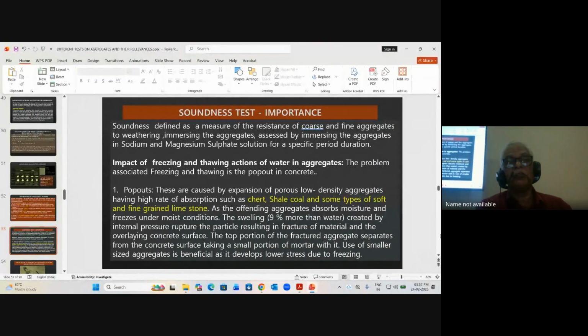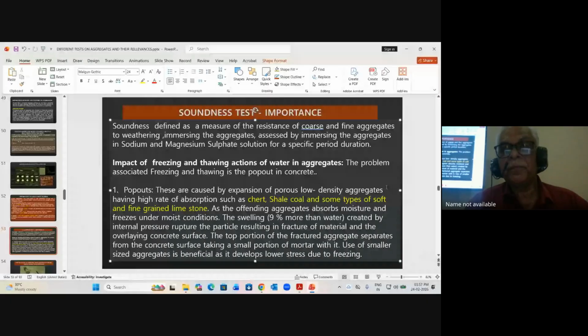Now we come to the soundness test. This test is conducted by immersing the aggregates in sodium and magnesium sulfate solution for a specific period of duration. This is very critical for freezing and thawing actions of water in aggregate.